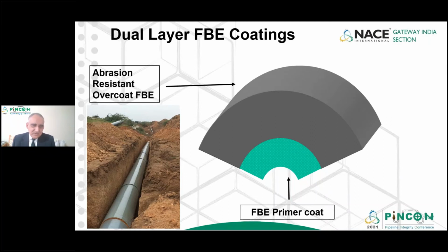This combined coating system resists a temperature up to 110 degrees Celsius. So pipelines which are operating at, say, minus 30 to 100 degrees Celsius can utilize this technology. It's very fast and easy to apply as compared to 3-layer. This system can be applied with a greater speed, so the pipeline project can be completed on time. Easy to handle, and very easy to inspect and repair the coating defects. And the total thickness required for corrosion protection in this case is only about 800 to 900 microns as compared to polyethylene, which is 3 millimeters. So this is consuming less quantity of coating material. It's more economical and with higher performance.